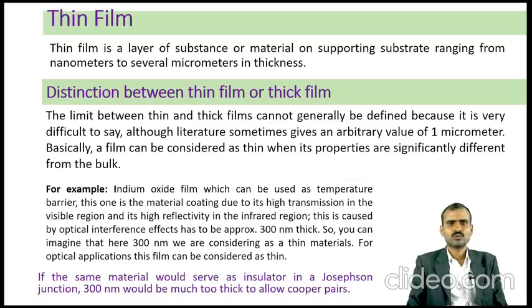If the same material would serve as an insulator in a Josephson junction, 300 nanometer would be much too thick to allow Cooper pairs. Cooper pairs are what pass through the material we use in between the two superconducting layers. So, through the oxide, for this application, that indium oxide film should have a thickness of only 2 nanometer. So, now my big question is whether we are going to call 2 nanometer thin or thick, and which one is thicker, 300 nanometer or 2 nanometer. Here are the answers.